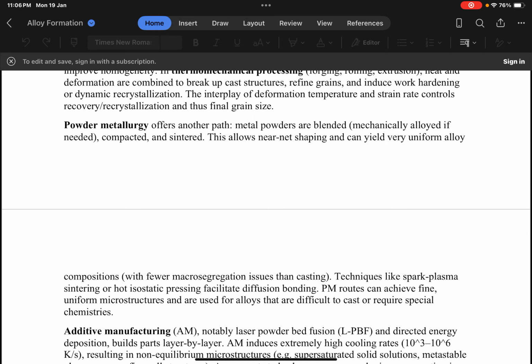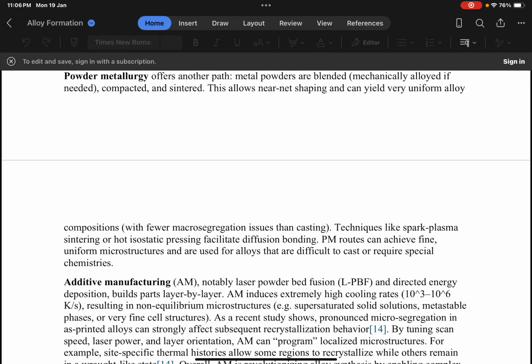Next method is powder metallurgy. Powder metallurgy produces fine and uniform microstructures with minimal segregation. Metal powders are blended mechanically, alloyed if needed, compacted, and sintered. This allows near net shaping and can yield very uniform alloy composition with fewer macro segregation issues than casting.